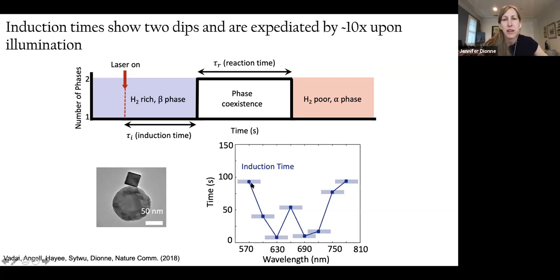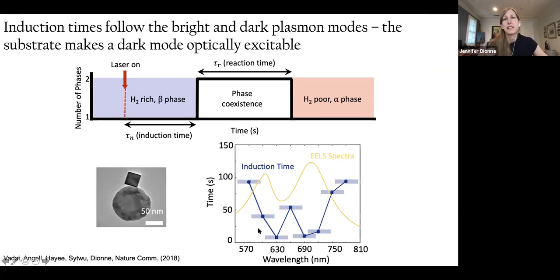And here I'll just mention that we had passed our light source through a bandpass filter, and the length span of each of these bars corresponds to the bandwidth of the illumination. So each of these dips where we have significantly increased kinetics, in some cases up to 10x increased kinetics, correspond to where we have plasmon resonances. So if you look at the EEL spectra of this mode, we wind up seeing two peaks right around 630 and about 720 nanometers that correspond to the plasmon resonances.